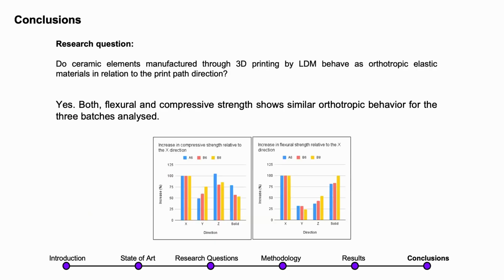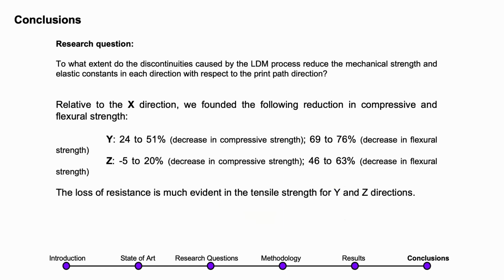Our conclusion is that yes, both the flexural and the compressive strength show orthotropic behavior for the three batches. We observe a loss for the Y direction of 24 to 51% in compressive strength, and 69 to 76% in flexural strength. And for the Z direction, a 5 to 20% decrease in compressive strength, and a 46 to 63% decrease in flexural strength.